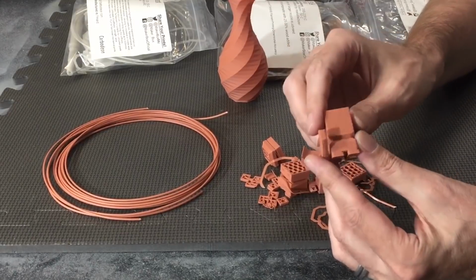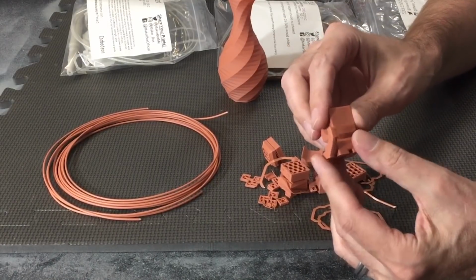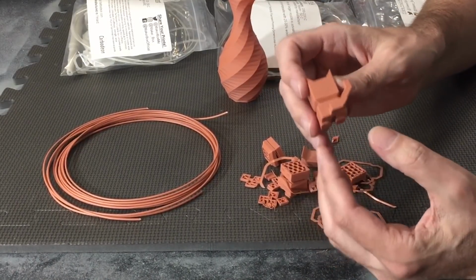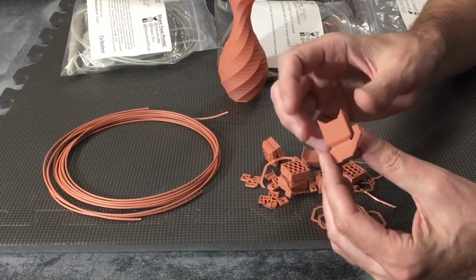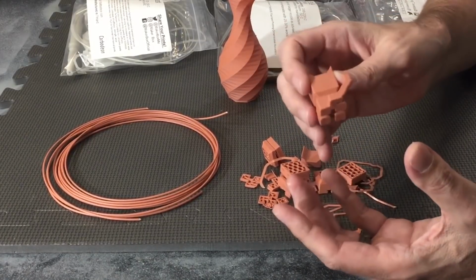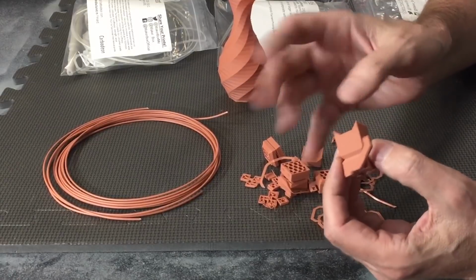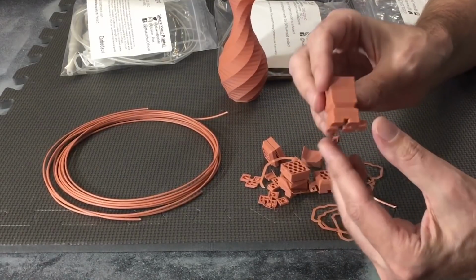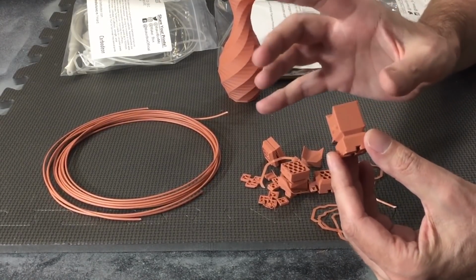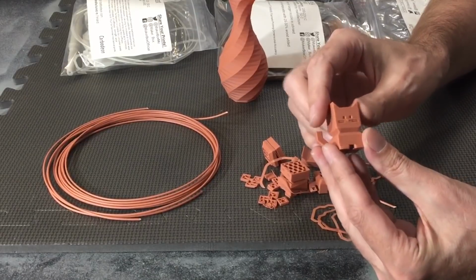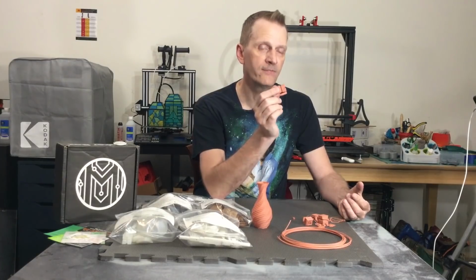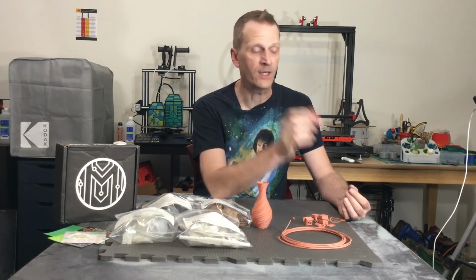I did hear a few pops during the print, which indicated there might be some air bubbles. But again, when you put additives in any kind of plastic for heated extrusion, there is the fear that you could add air bubbles or create air bubbles along the line. But I didn't see any super big ones. There was a few small ones in the surface finish. But again, it printed perfectly, and there was no interlayer warping going on.